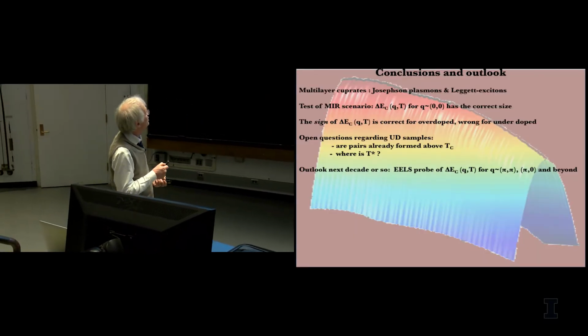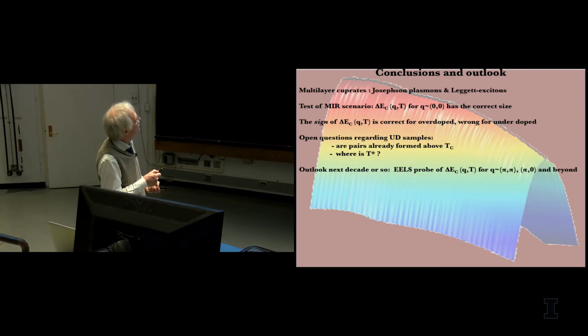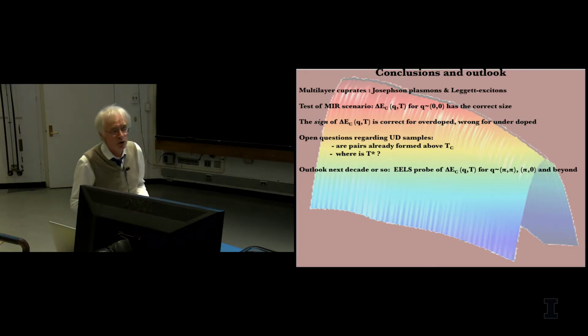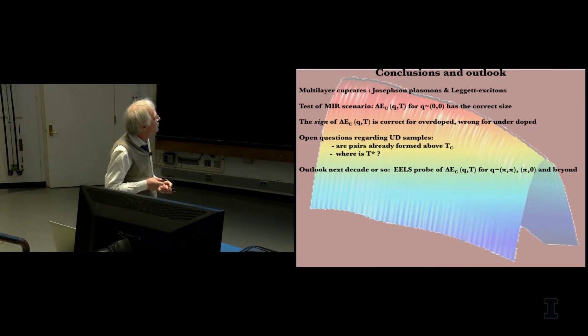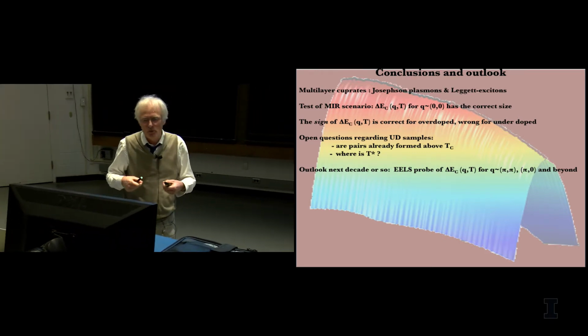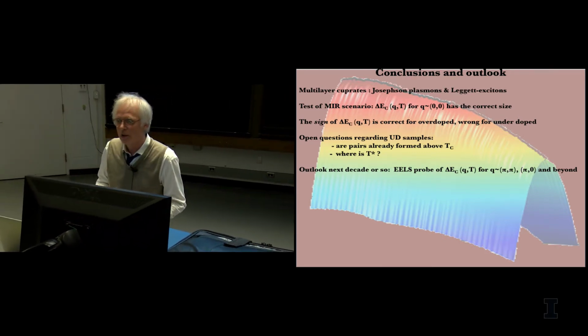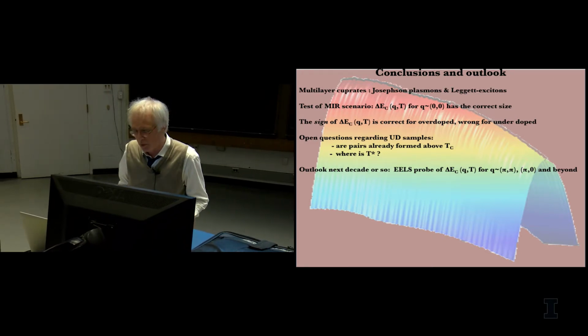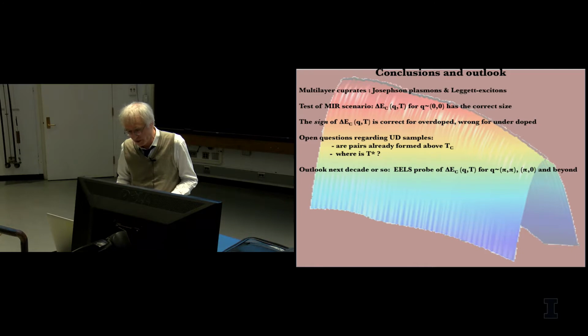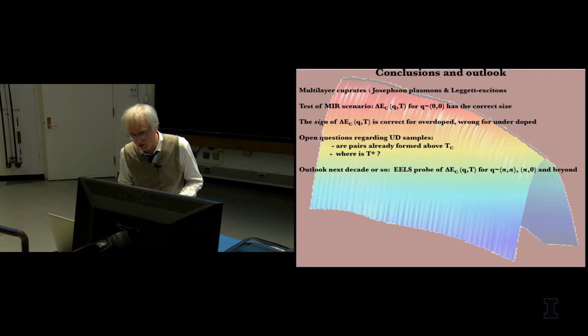Okay, that brings me to the conclusions and the outlook. So the multi-layer cuprates, there you have Josephson plasmons and Leggett excitons. If you do the test of the mid-infrared scenario, then we find the correct size more or less, but the sign is not always correct. And there are a couple of open questions. For the underdoped samples, are pairs already formed above Tc? And where is the T star, if there is a T star at all? It could also be a crossover, as Mike said. For the next decade or so, we need EELS probes of the same quantity, so we actually have to measure really the correlation function in momentum space, from which we calculate also what the direct space correlation function looks like. And we have to do that in very small and precise temperature intervals.